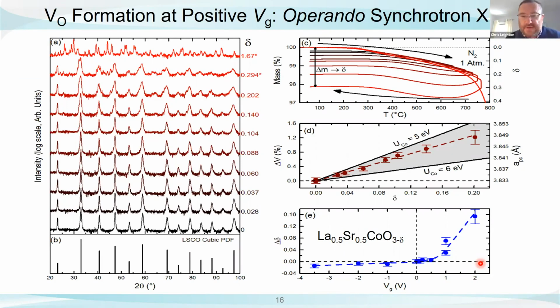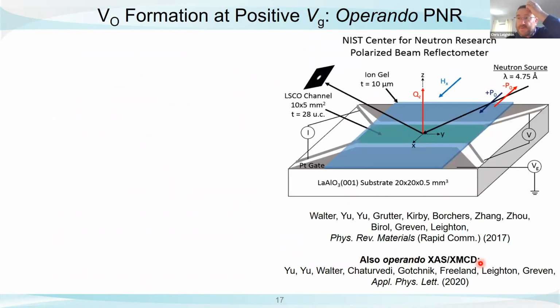Now, one of the things that really surprised us about this is we're applying a surface electric field. The film's quite thick, it's 16, 17 nanometers thick, and yet it looks like the entire X-ray diffraction pattern shifts. It looks like the whole film is being reduced all the way through its thickness. So we were a bit skeptical about that, so we decided we would apply a depth-sensitive probe, and we used polarized neutron reflectometry, PNR. So this is, in principle, a fairly simple technique.